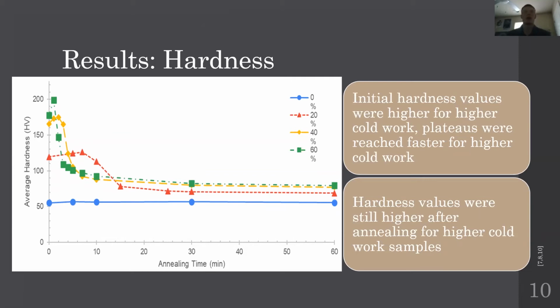And one interesting thing to note about each of these trends is they follow the same pattern of a slight increase followed by a sharp decrease and a plateau. And the interesting thing is that as you increase the cold work, the time that it takes to reach that plateaued value decreases. So this relates to the hypothesis that Tony was talking about, that perhaps because these higher cold work samples have a higher internal strain energy, they require less thermal energy to begin the process of recrystallization and recovery.